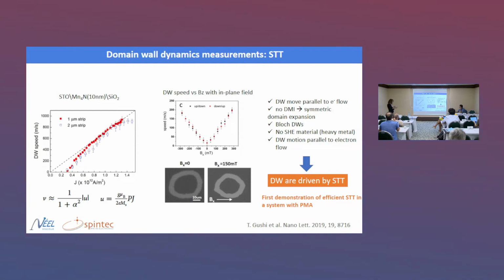If you take the 1D model for spin-transfer torque driven domain wall motion, you see that the efficiency is essentially given by the ratio between spin polarization and magnetization. So we have a system with a small magnetization because it's a ferrimagnet. And then by fitting this curve, we found out that the polarization was about 65%, which explains why we have this large domain wall movement.